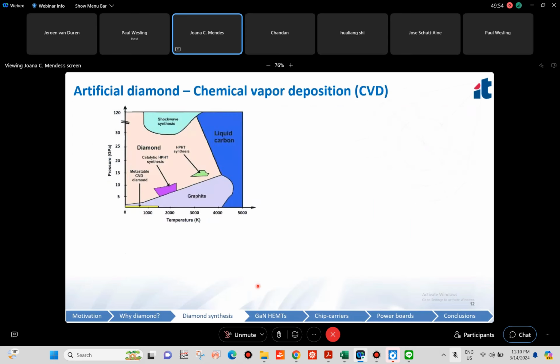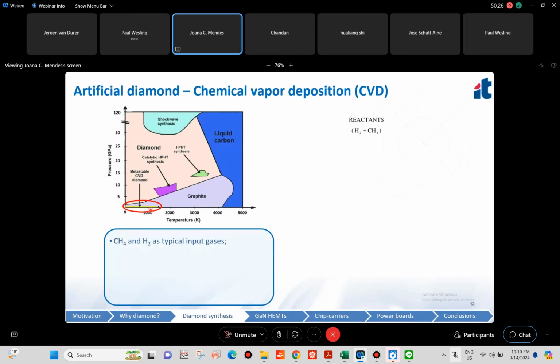But then we can also fabricate diamond by chemical vapor deposition. And here you can see the phase diagram of carbon. This will tell us, depending on the temperature and on the pressure, which type of carbon allotrope will be formed. So graphite, liquid carbon, diamond here at the HPHT regime. And you can see that we have here the metastable CVD diamond phase below atmospheric pressure and at moderate temperatures, where we can also fabricate diamond. And how can we do it? Well, to begin with, the carbon is supplied as a gas.